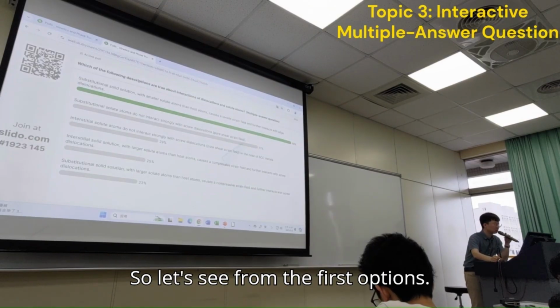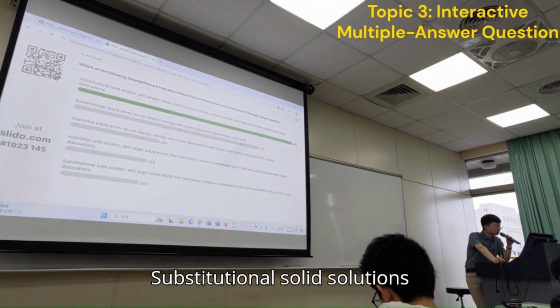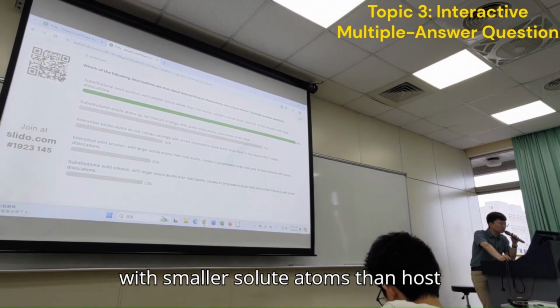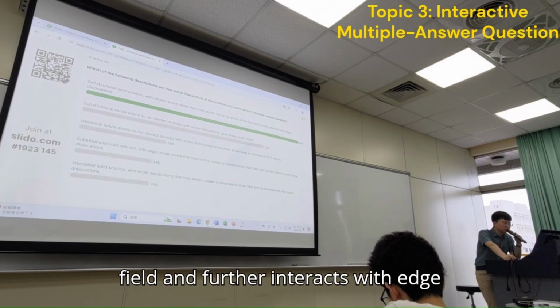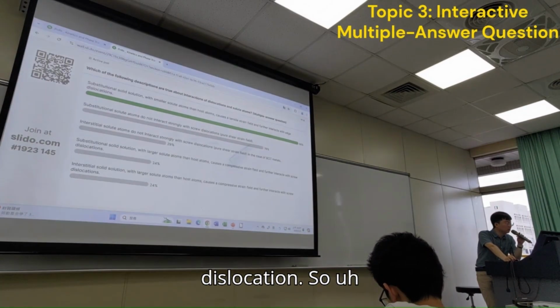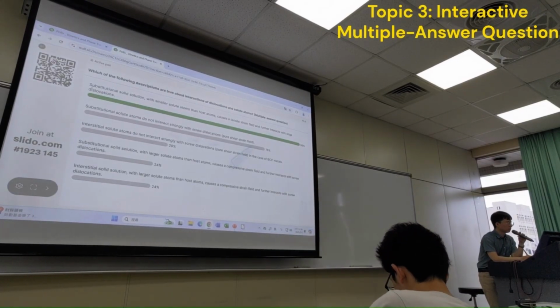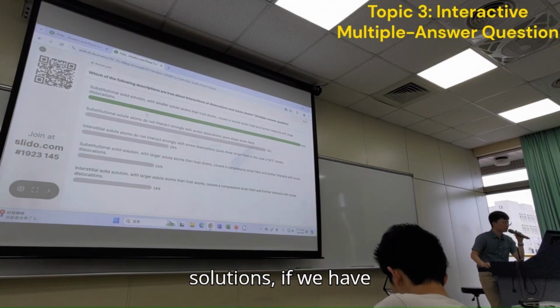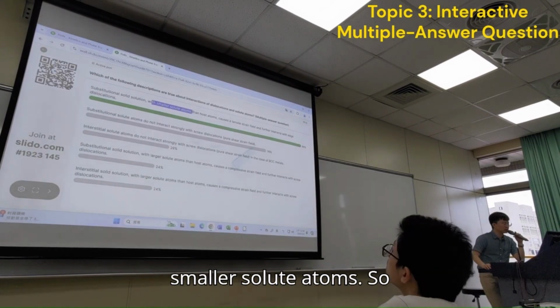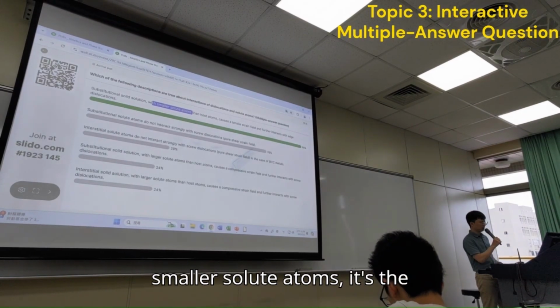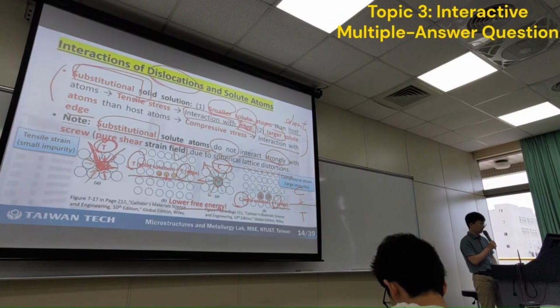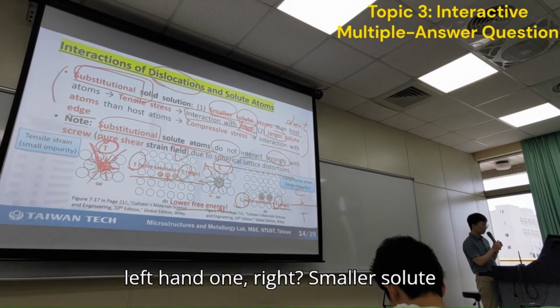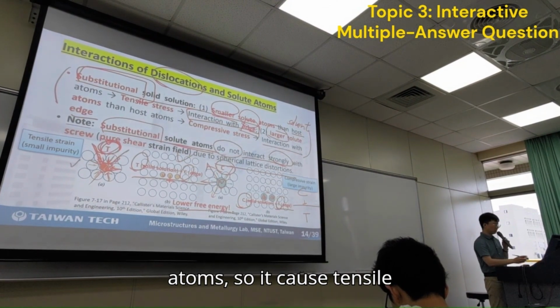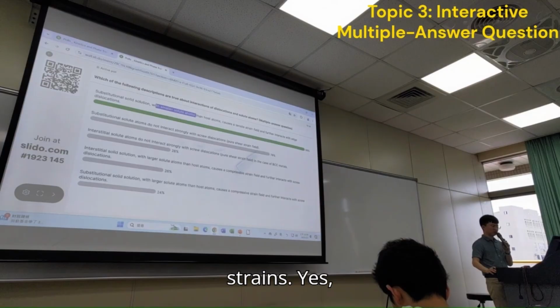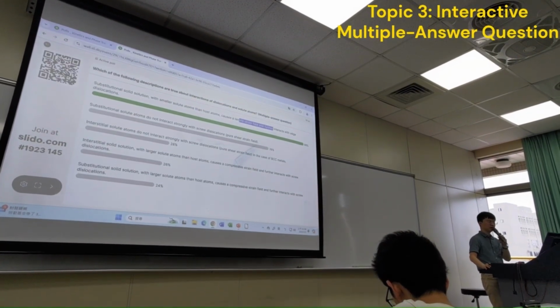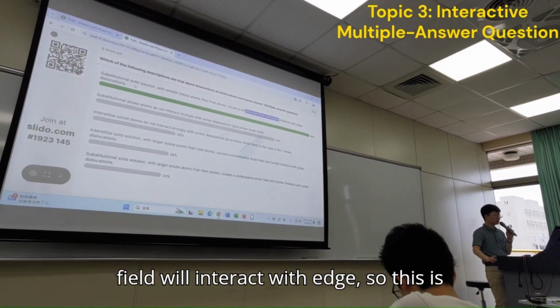Let's see from the first option. Substitutional solid solutions with smaller solute atoms than host atoms cause a tensile strain field and further interact with edge dislocation. So for substitutional solid solutions, if we have smaller solute atoms, which is the case for the left-hand one, it causes a tensile strain field. Yes, and tensile strain fields will interact with edge dislocations, so this is correct.